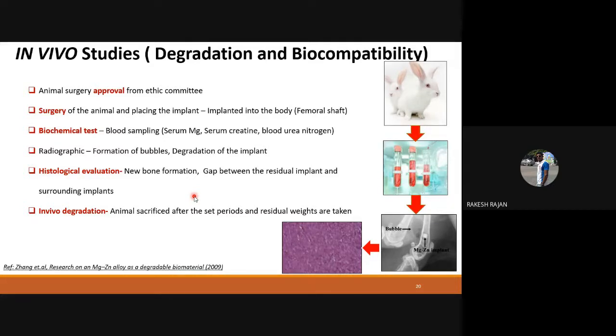Then radiographic tests. This is where you can see it in the image. In the radiographic image, magnesium zinc implants are placed in the femoral shaft, and bubble formations happen at a certain period of time. So you need to understand whether this bubble formation is happening or not, or whether it vanishes after a certain period of time or not. And then we will be taking histological evaluation, the new bone formation and the gap between the residual implant and the surrounding bone.